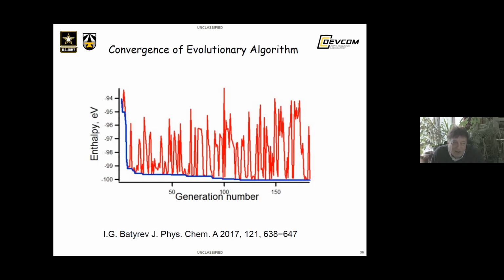So there is always room for improvements of the papers on evolutionary predictions. Computers are getting bigger to handle long evolution and larger population size to handle larger unit cells of predicted structure. We adjusted USPEX code for DOD supercomputers and were able to perform the longest, to my knowledge, evolutionary simulation up to 150 generations and about 4,000 structures. Population size is limited by 40 atoms.